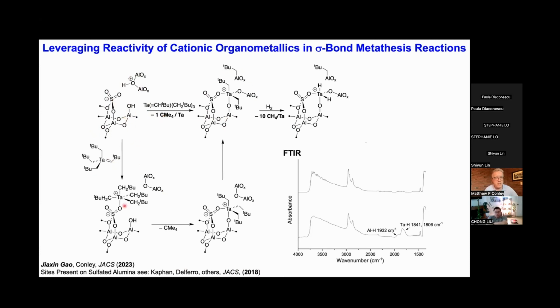The way we think this happens is we protonate the alkylidene, which is analogous to what has been shown for silica. And then nearby OHs react with this reactive electrophilic tetraalkyl fragment to form the trialkyl organometallic that's nearby an Al-O-Al bridge that opens this by alkyl transfer to generate our dialkyl organometallic. In this sort of structure, you would expect 3 C alpha carbons if you selectively C13 label the organometallic at the C alpha, and that's exactly what you see. You see 3 chemical shifts that are characteristic of these 3 different sites.